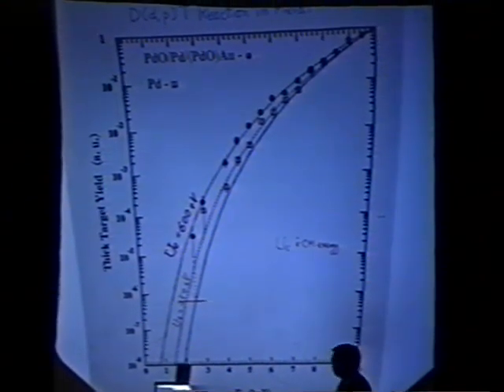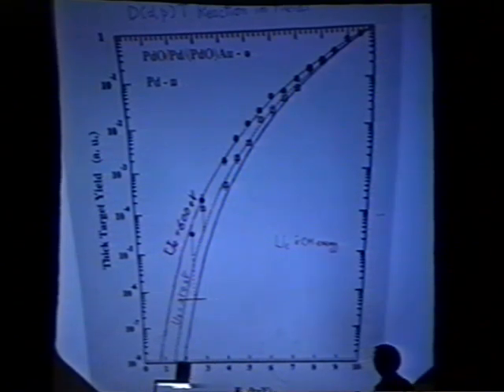And if you see the palladium oxide data, the enhancement already started at much higher energy, maybe 9 kV or 8.5 kV. And we got the data down to 2.5 kV. Here, the enhancement is something like 50 times. And if we parameterize the same way as we did for the titanium and the deuterium, we got a screening potential of 600 eV for the palladium oxide and 250 eV for the palladium. Since the chairman is now standing up, I have to stop here.